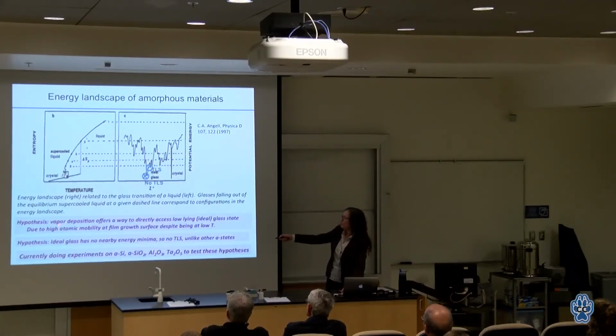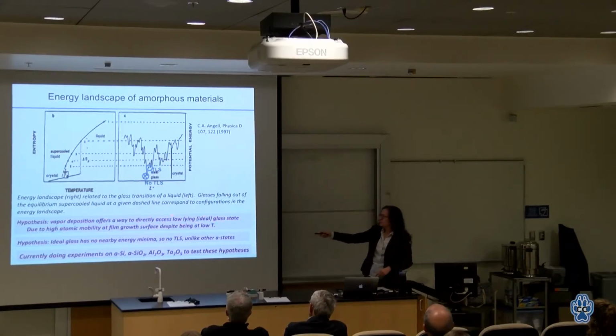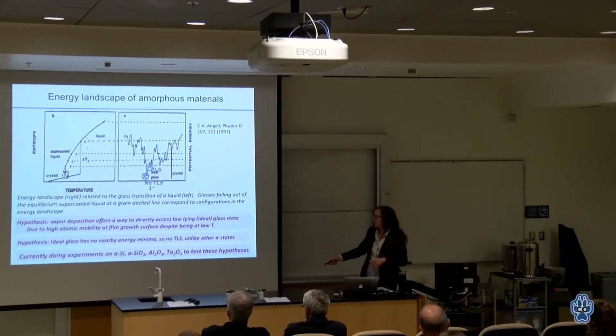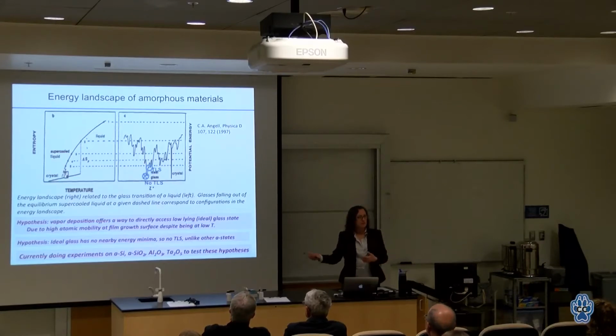So we have these two hypotheses. One is that vapor deposition offers us a way to access that low-lying ideal glass, which you can never get by liquid quenching, because you can grow at that temperature and have surface mobility. And two is that the ideal glass has no nearby energy minimum, so no TLS. We're currently doing experiments to test those two hypotheses.